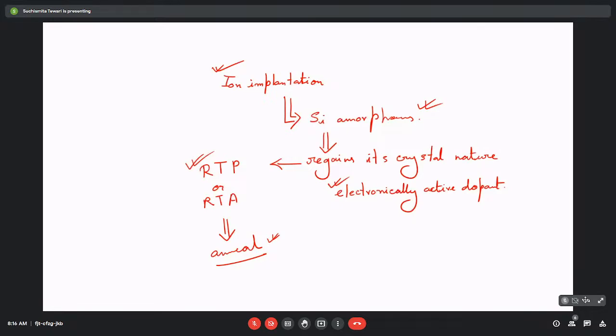Now the question comes, if the diffusion is taking place somehow, then obviously the Gaussian profile or the penetration depth that we were talking about must get distorted or exceeded. So in that case, what we can do is implant the ions up to a position which is a little bit less than the desired junction depth. So after the diffusion, that is after the spreading of those dopants within the silicon, while the silicon is regaining its single crystal nature, the junction depth cannot be exceeded. So that is one technique that we can use. And since we are doing that anneal step adopting rapid thermal processing, the duration for which the silicon remains at high temperature is very, very less. So the diffusion happens, but in a very controlled manner. So it doesn't deviate very much from the Gaussian profile that it has taken.